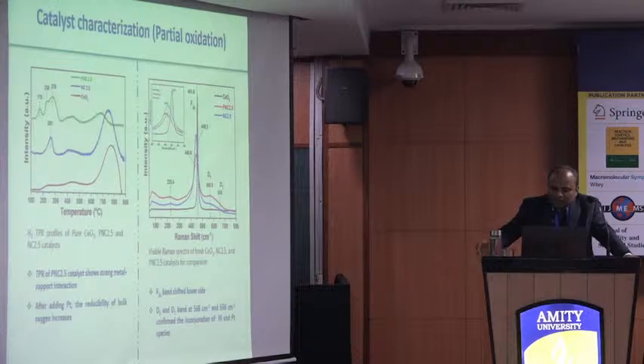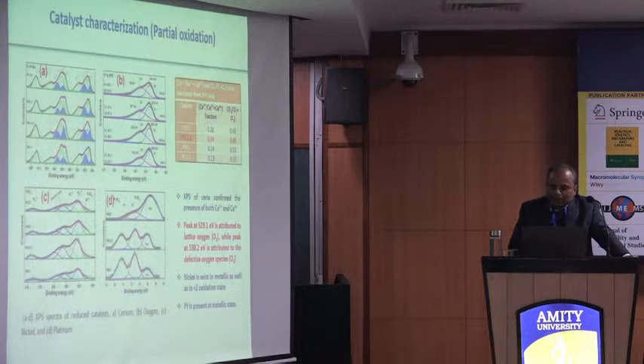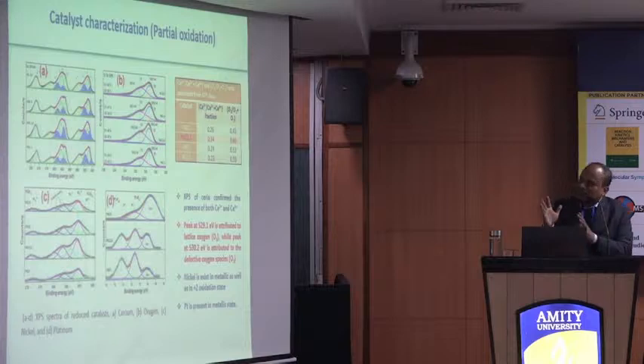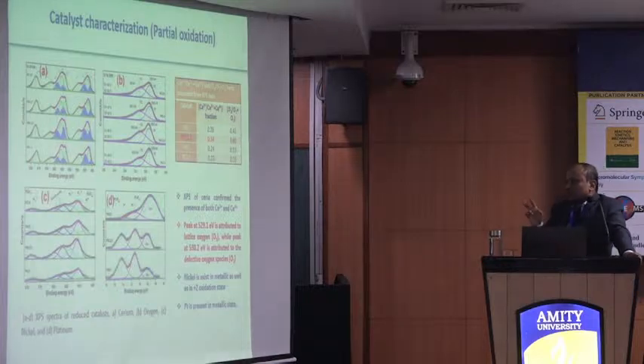Then we characterized by TPR, which you can see here, and we have also done some Raman. From the Raman, we can see the D band is shifting. That means nickel and platinum are incorporated in the ceria lattice. We have done the XPS study. We can see here that for platinum 2.5, the Ce3+ concentration is higher. That means we have more vacancy sites in the catalyst. From the oxygen spectra, you can see the peak at 529.1, which is the lattice oxygen, and the peak at 532.2 is attributed to defect oxygen species. We found that our catalyst has more defect sites, and that is the active phase on the surface for this reaction.